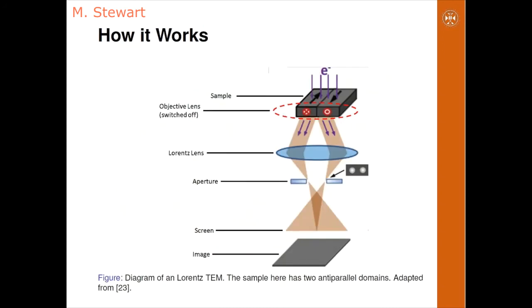So let's picture that all together. Electrons are fired in from the top towards the sample. This sample has two antiparallel domains, and each of those will deflect the electrons differently from the Lorentz force. Then the electrons are focused by the Lorentz lens. The intensity across the screen gives us our image. Now, one thing to consider is that here the aperture has been positioned to produce a focused image. But unfortunately, this will always give uniform intensity across the image, so no contrast. In practice, there's a clever experimental trick to give us contrast, and that's to raise or lower the aperture a tiny bit, which will slightly defocus the image. But if you can imagine just raising the image plane, there, we'd see a dark fringe right where the sample's domain wall would be.